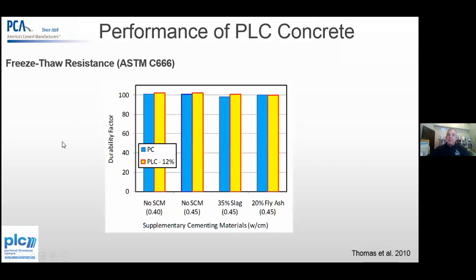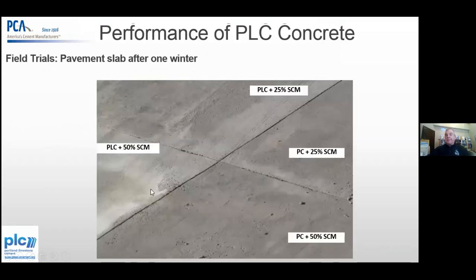666, kind of comparable durability factor, almost 100 all the way through, whether it's a PC, Portland cement, or Portland limestone cement. This was just a 1-year shot. I don't have the update, this is like 10 years ago. Actually, this trial by Hooton and Thomas was done in Quebec in 2005, even before it got into the specification in 2008 in Canada. That pavement's been down, and there's been no reported issues with it.